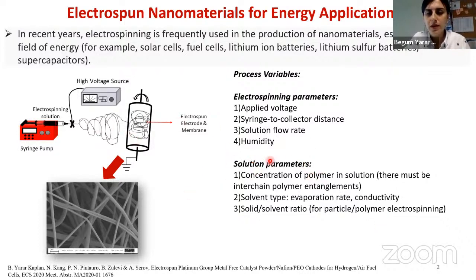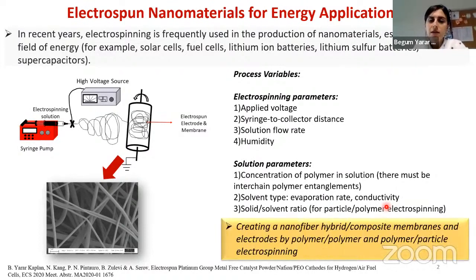The other one is solution parameters. This is really important if you are adding additional particles such as carbon or active material or catalyst into your nanofiber structure. The concentration of the polymer solution is really important here. The solvent type is really important because evaporation rate is really important when you are doing the electrospinning. And as I mentioned before, the solid to solvent ratio is really important if you are doing polymer particle electrospinning.